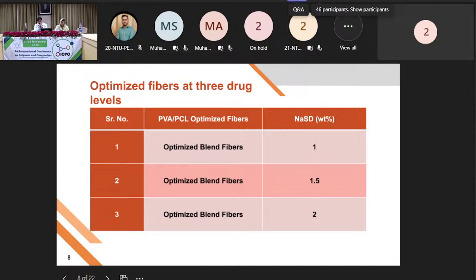We used sodium sulfadiazine as a model drug in the optimized blend ratio. The sodium sulfadiazine used is in the range of 1 to 2 weight percent in the materials.